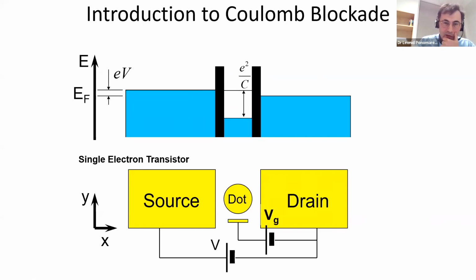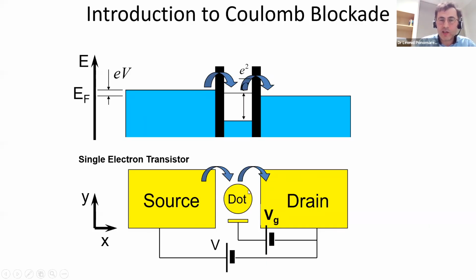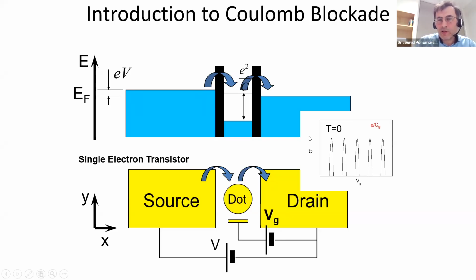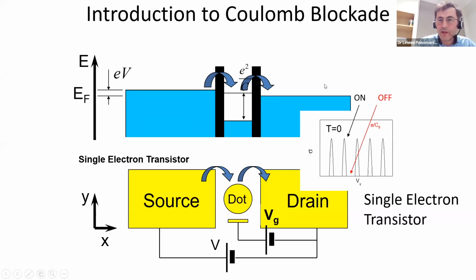So we can use this effect to make transistors. If we make a gate to this dot, we can change the electrostatic energy of the dot by applying gate voltage. Then once this level, which appeared due to Coulomb blockade, gets into the energy window between source and drain, current can start to flow again. If we plot the conductance of such a device as a function of applied gate voltage, we will see some peaks. These peaks appear exactly when this level is in the energy window between source and drain. You can see here there is an on state when the device is conducting, and there is an off state in between these two peaks. So this device is called a single electron transistor.